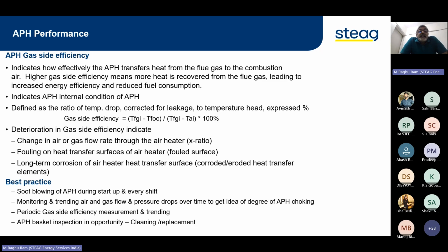Deterioration of gas side efficiency indicates change in air or gas flow rate through the air preheater, fouling on heat transfer surfaces, or long-term corrosion of air heater heat transfer surfaces because of the high SOx content or condensation at the cooler zones of the air preheaters.